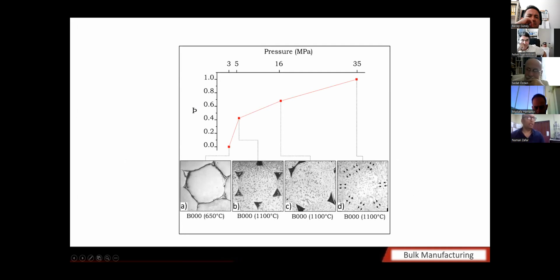For the pressure, what we did was hit and trial. Lower temperature, low pressure, then we increased the pressure to 35 megapascal, and eventually we saw that these wires are able to join at this level. In this place, you can see that there are no voids. At the macroscopic level, you cannot see voids. So we decided that our treatment temperature should be 1100 and the pressure should be 35 megapascal. This parameter is defined to see the complete bonding.